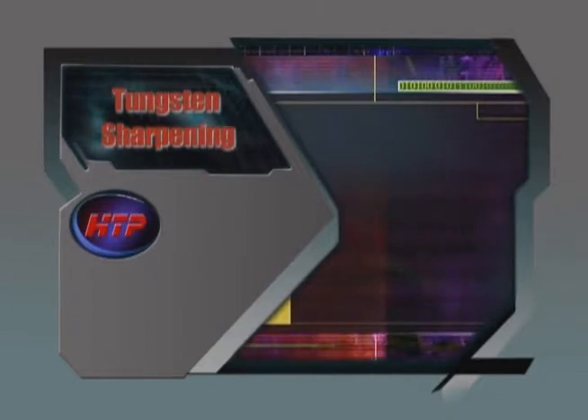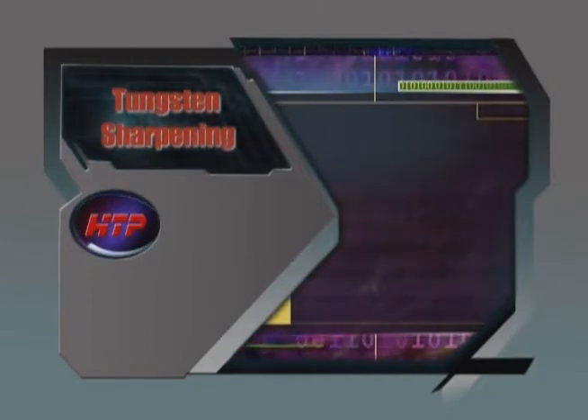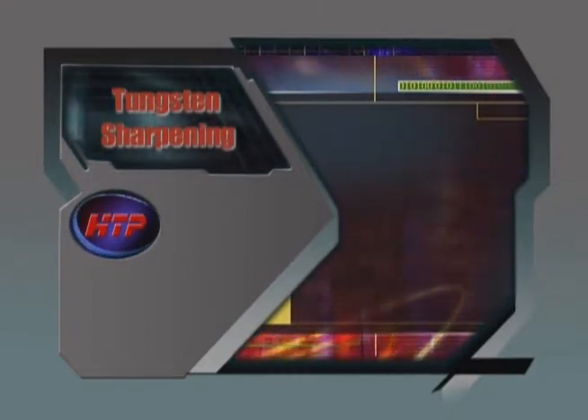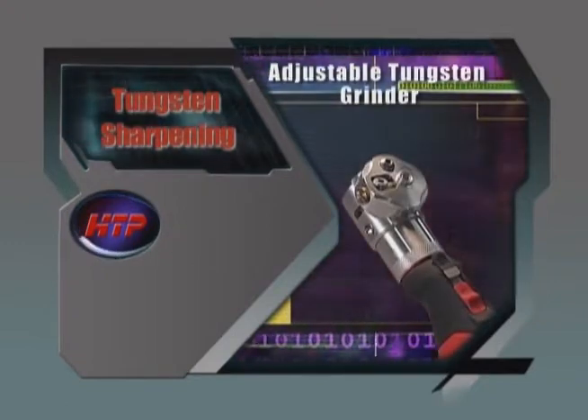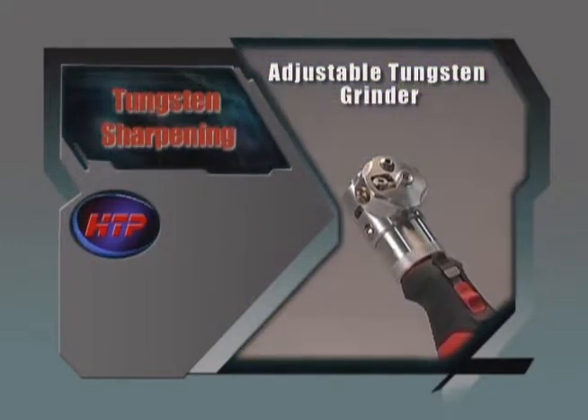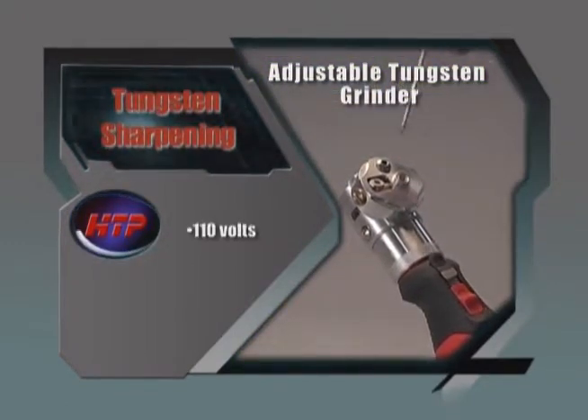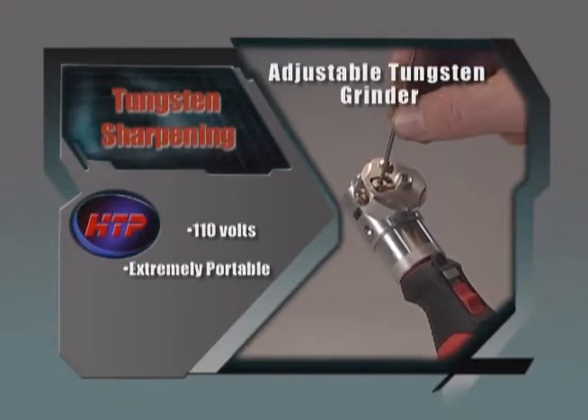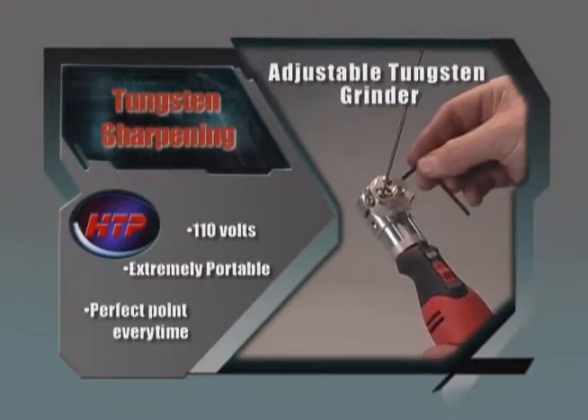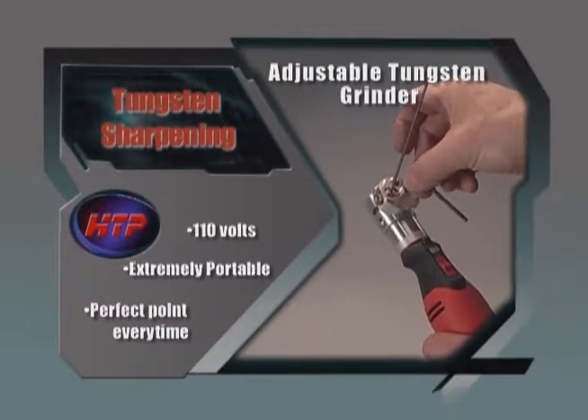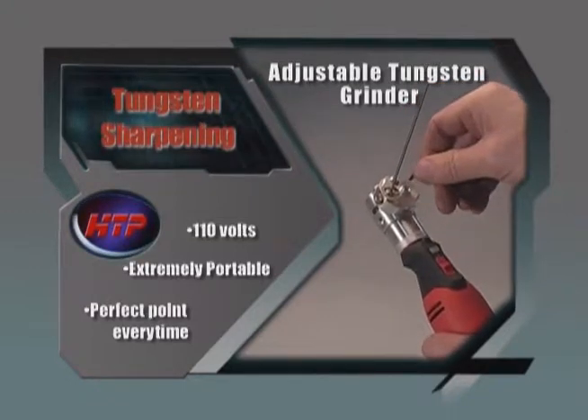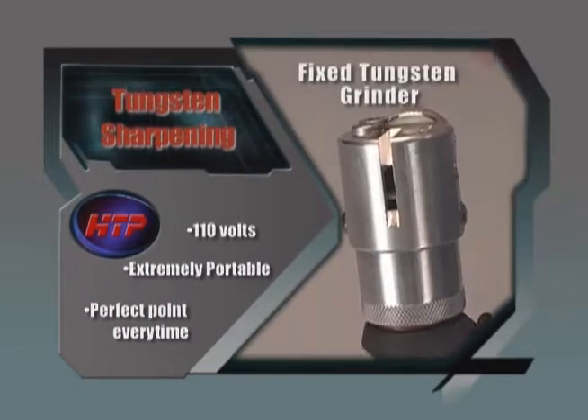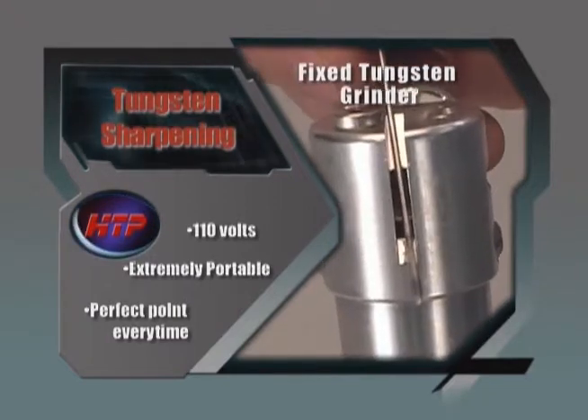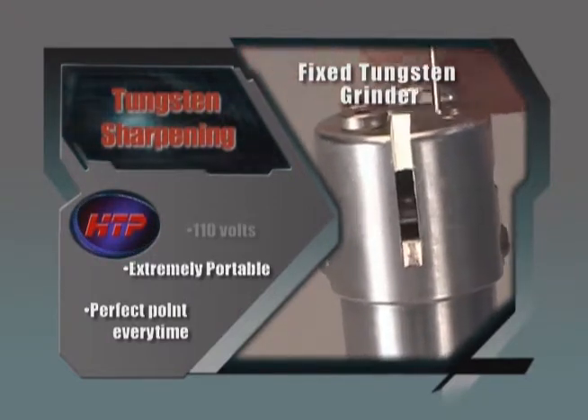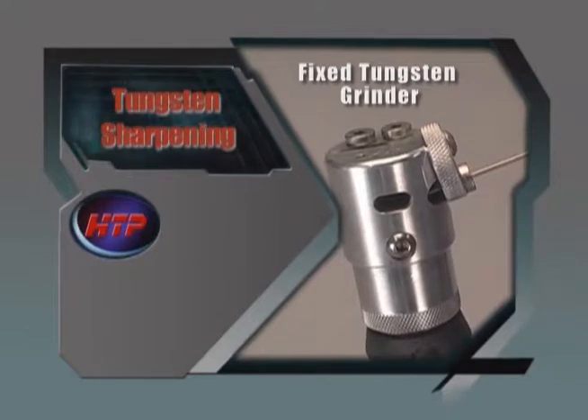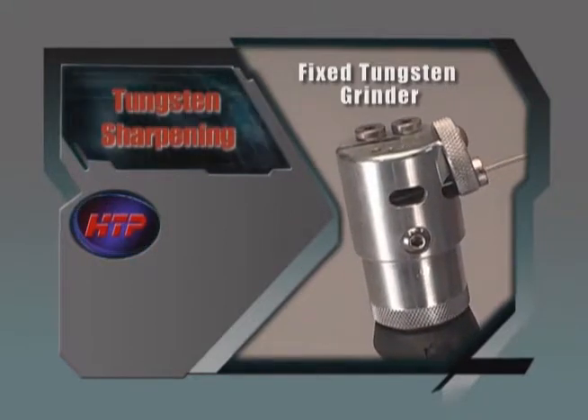If you are unable to have a dedicated grinding wheel for sharpening tungsten, then you may want to consider the HTP tungsten grinder. This tool operates on 110 volts, is extremely portable, and gives you a perfect point every time. It is available in two models, a fixed angle and an adjustable angle. If the tungsten has been contaminated, use the tungsten grinder to cut off the tungsten prior to grinding. Then insert the tungsten into the grinder to sharpen.